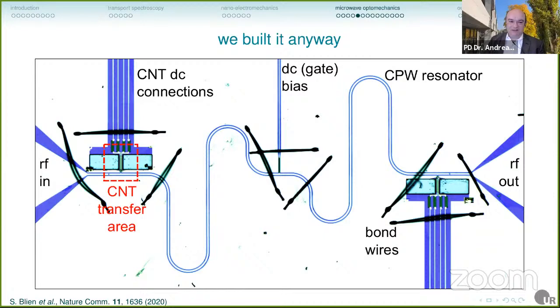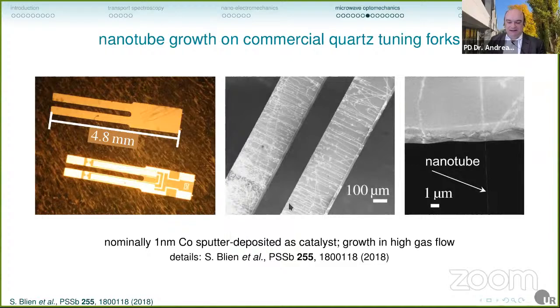Just imagine you do a really complicated chip preparation, and then your last fabrication step is one that likely destroys it. The big advantage of this technique is that we can insert the tube, and if it doesn't work, we can insert it again. The difficulty is that you don't just get single nanotubes here, you also get bundles. But on the other hand, a priori, I see no reason why these should be dirtier than the other ones, because it's more or less the same process. We use a different catalyst a little bit. We use cobalt instead of the nanoparticles that we used in Delft and also later used in Regensburg. But apart from that, it's the same gases.